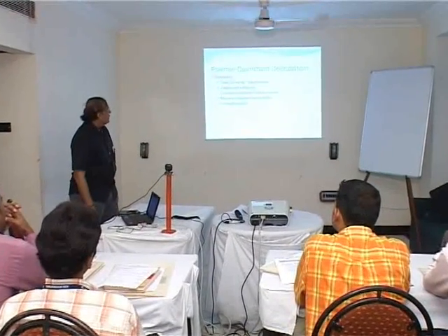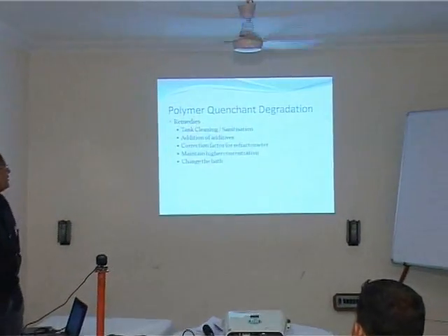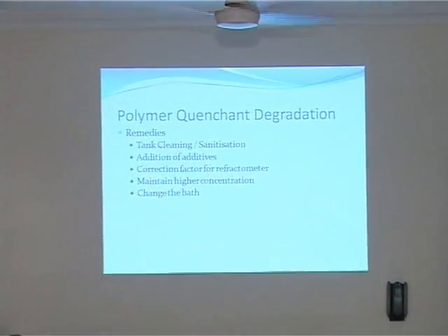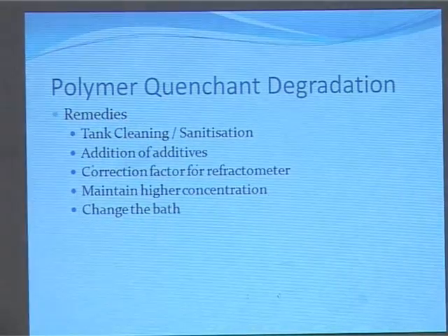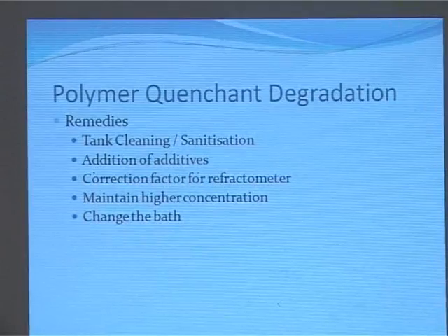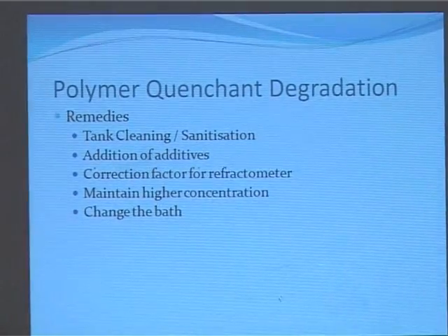The remedies for that: you have to clean the tank or sanitize it as and when required. You go on adding, and the correction factor for the refractometer you have to keep changing. Then always maintain a higher concentration of the polymer, and change the bath. If you do these things, you will find that the polymer quenchant can be used for a longer time.